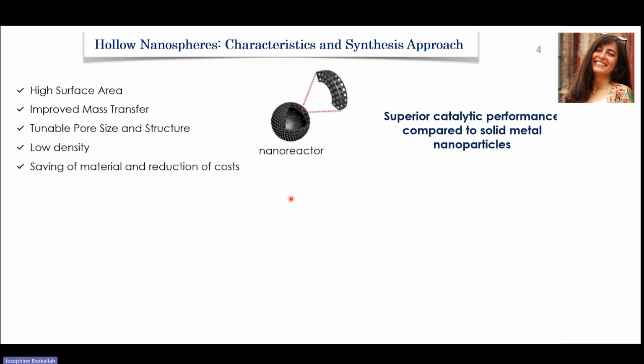With an empty interior, this hollow cavity functions as a confined space and acts as an engineered reactor. By confining reactants in this controlled environment, these nanoreactors promote efficient and selective chemical transformation. Now, this design with optimized morphology mainly offers a higher surface area than solid nanoparticles. It provides more active sites on the outer and on the inner shell for the catalytic reaction.